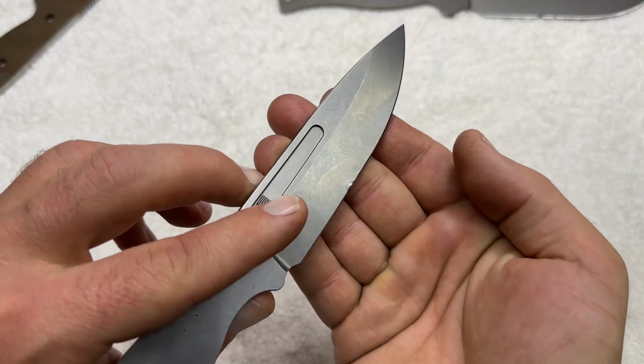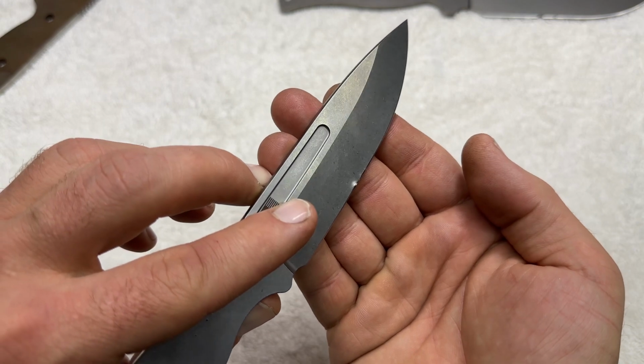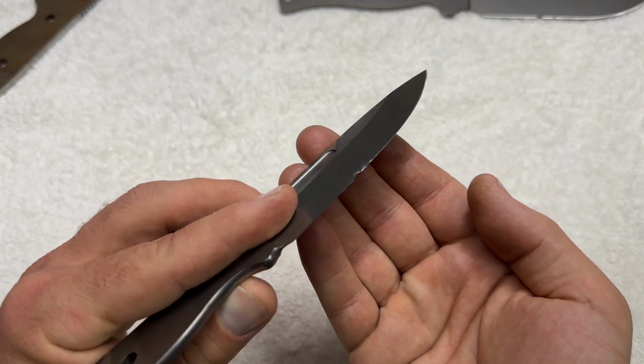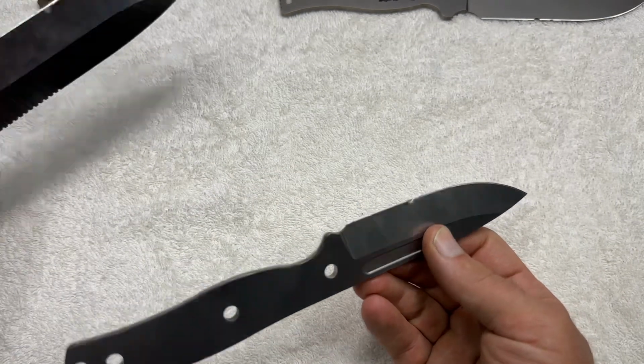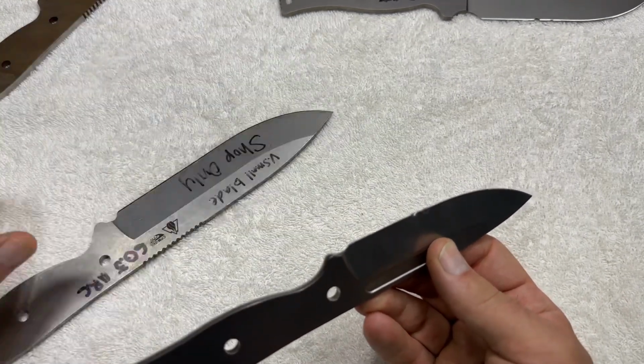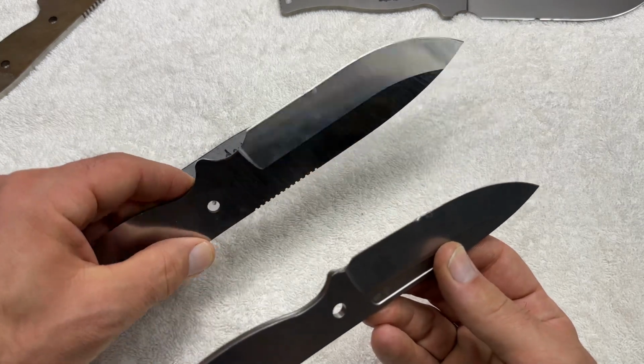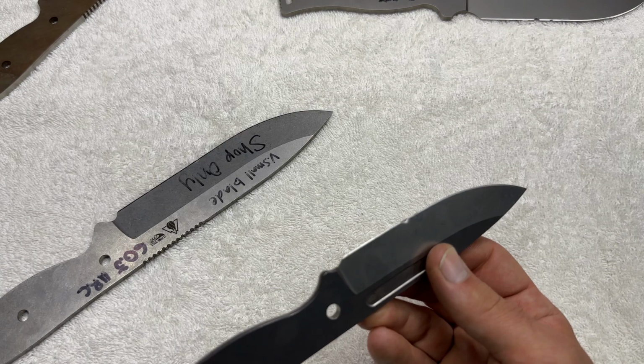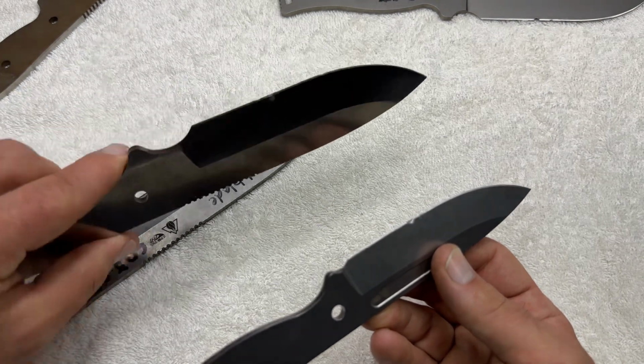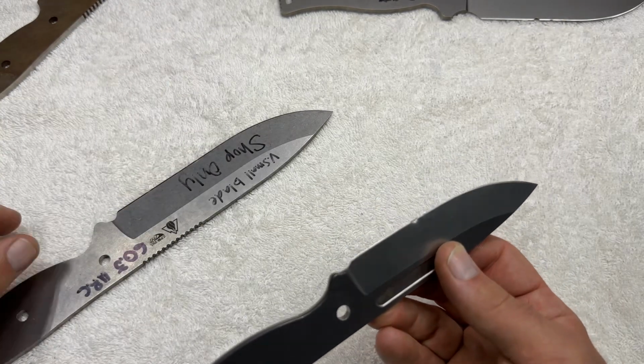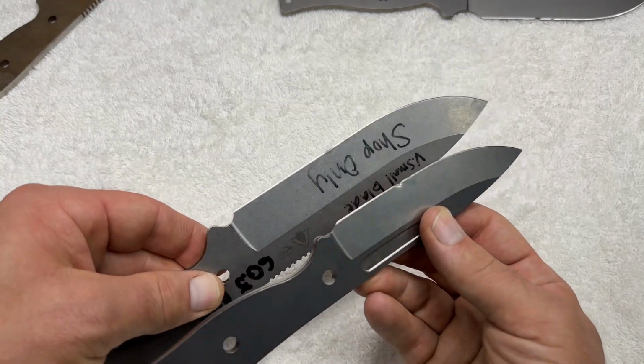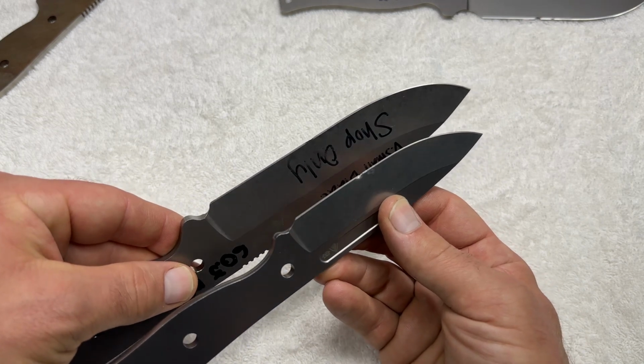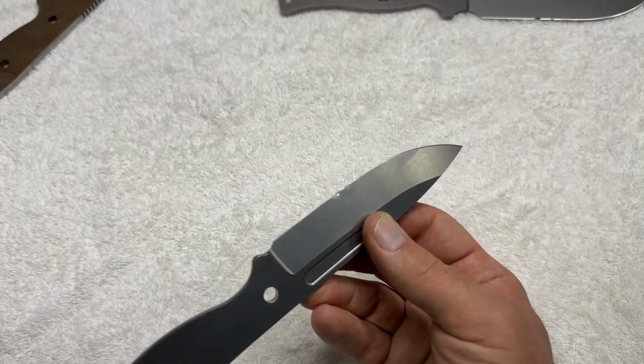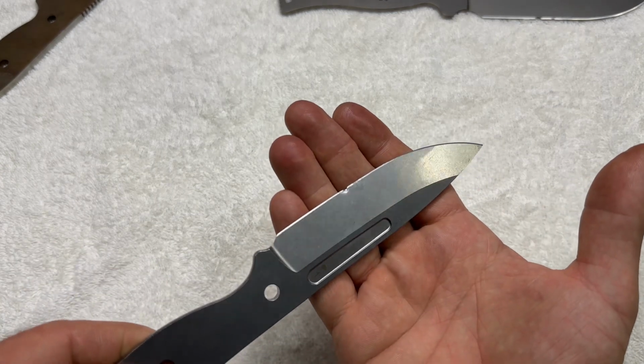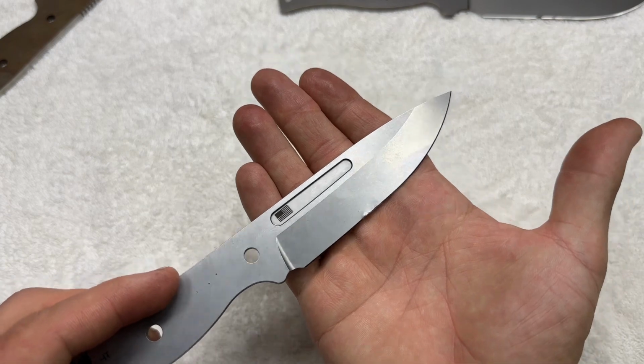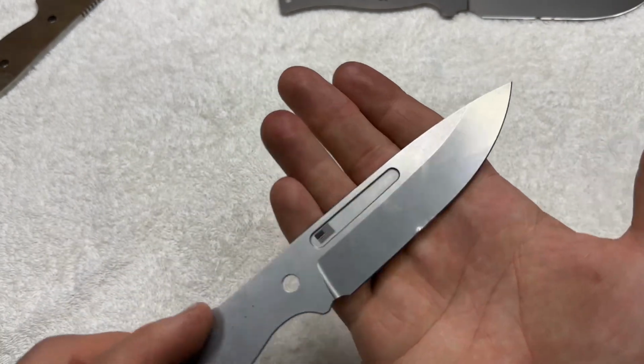but that just reconfirms my thoughts on that, and where there are different bits of feedback and durability standards on 3V across the industry. It's not all the same, even if the hardness is the same. That's within a half point of not that one. I mean, this is softer, so obviously it took the damage a bit better, but due to the really fast quench and our different handling treatments, this is still a stiffer edge than this, even at a lesser hardness. But these are within a half point of the same. They're the same edge weight roughly, and they had a much different result. So that was disappointing, but it's not unexpected. So all 3V is not the same. Please keep that in mind when you're buying things.